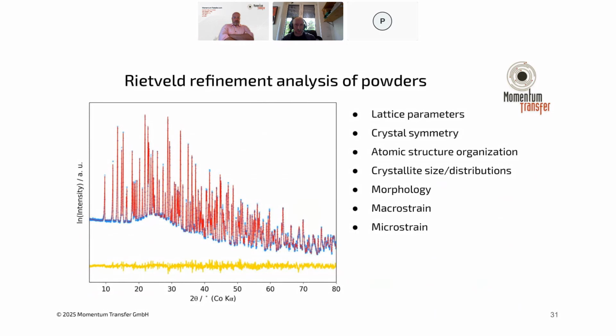So now I'll just quickly go through some examples. The most common method that we use to analyze the X-ray powder diffraction patterns is Rietveld refinement. Through this, we're essentially taking a model of the atomic structure of the material and simulating a diffraction pattern from that to match against the experiment. And then we can refine different parameters of that structure model to understand a lot of details of the material. This includes the lattice spacings and the contents, which is essentially the crystal structure and the density of the material, and crystal symmetry, which is responsible for not only the structure, but also a lot of the properties of the material. And then also microstructural information like crystallite size or size distributions, even the morphology in some cases, so if it's elongated or platy morphologies, or rather more isotropic. And we can also measure macro and micro strain as well.